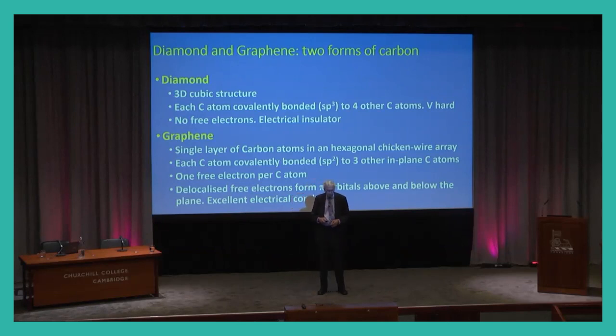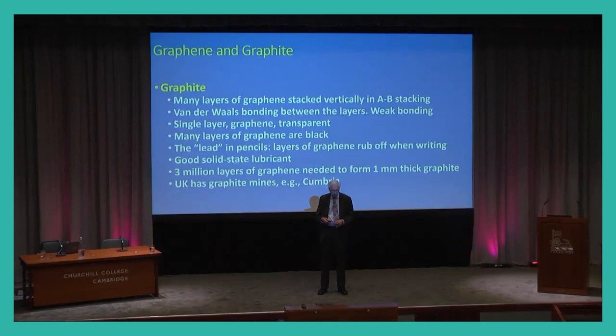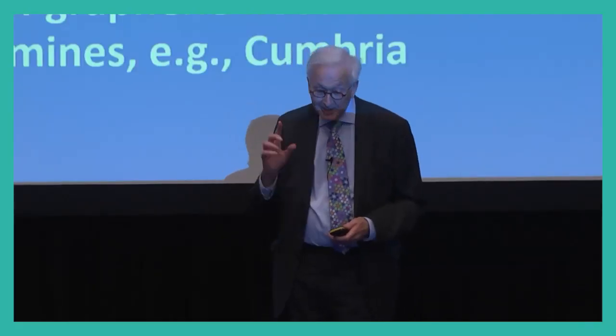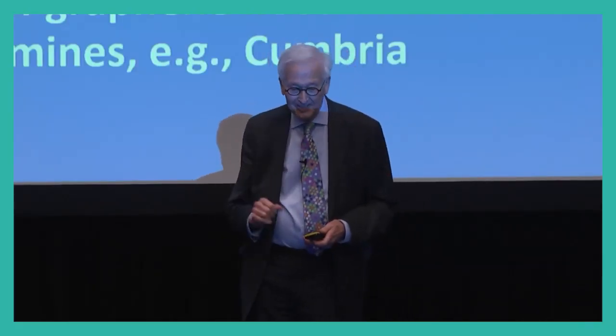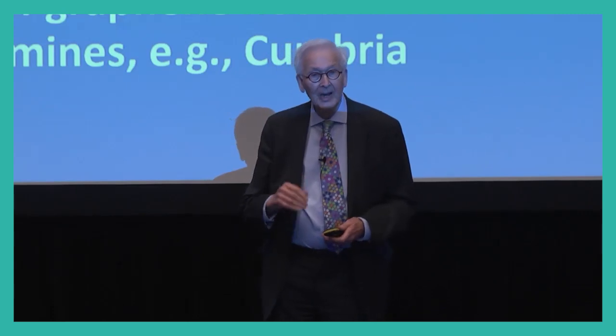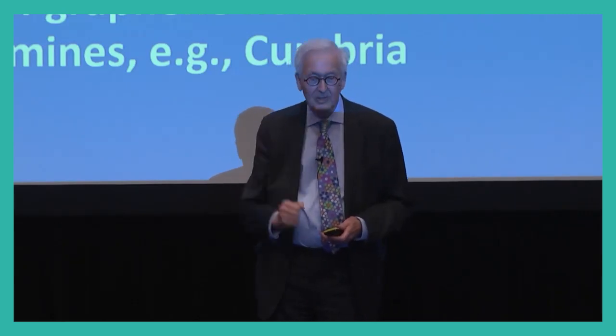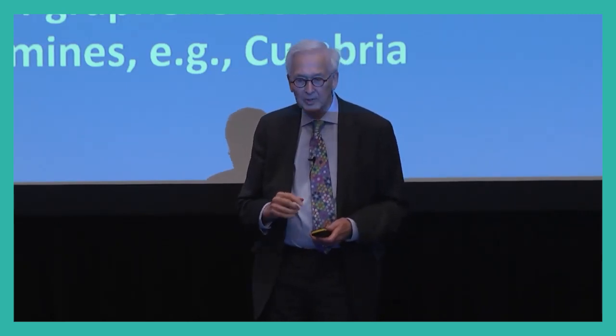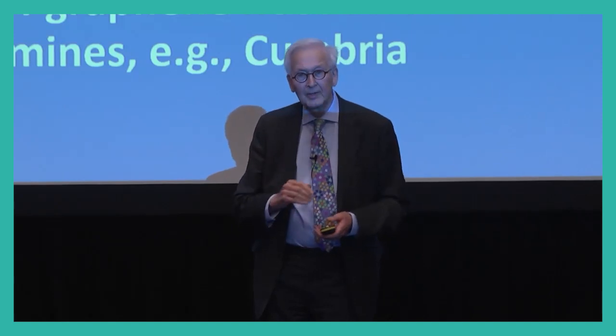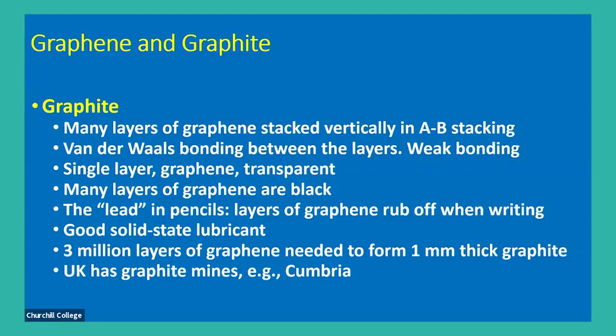And so this is really very important for graphene. Graphite, as we saw in the drawing, is many layers of graphene stacked vertically, in what's called AB stacking. And the bonding between the layers is called van der Waals bonding, which is very weak bonding. And so you can easily remove a layer of graphene from graphite.